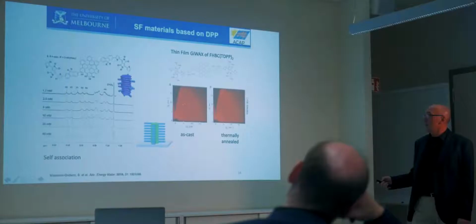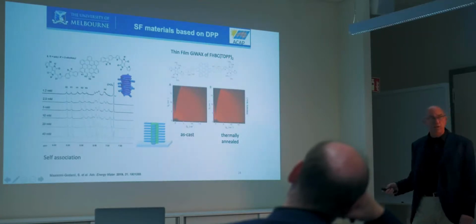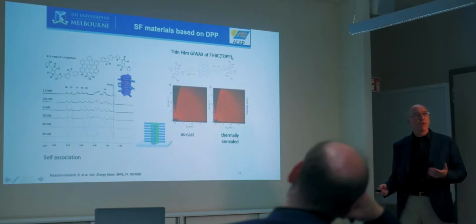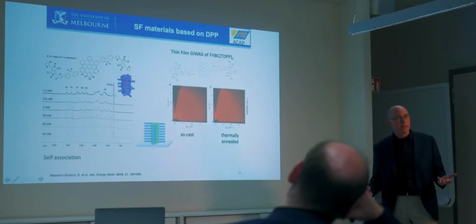We can extract association constants from this data, and we can see that it stacks through this hexabenzocoronene in sort of columns. And so then we did some X-ray work. This is grazing incidence wide-angle X-ray scattering that we did at the Australian Synchrotron, and we look as cast, and we basically see no structure. Sorry, this is not a very good image. We don't see a lot of structure here. So if we have crystallites, they're too small to diffract.